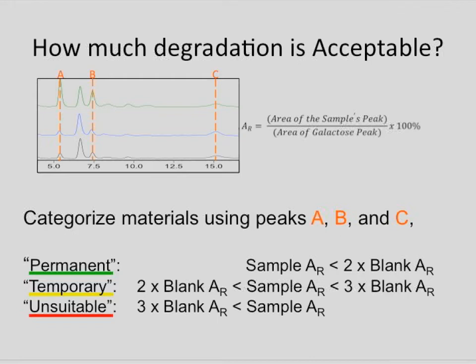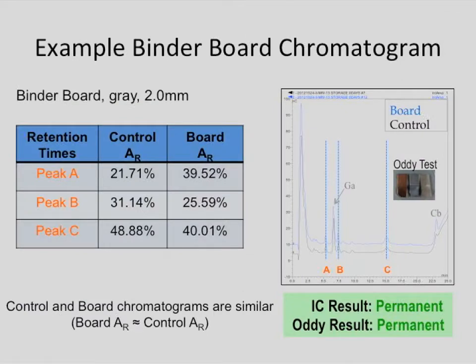Then we ask, how do you say it's temporary, permanent, or unsuitable for use with collections? This is arbitrary, just like the Oddy test, except now we have numbers to look at. We arbitrarily chose less than 2 times the area of the test material peak relative to the control. If it's between 2 and 3 times the control, we call that temporary. If it's more than 3 times the area, we call it unsuitable. That was totally arbitrarily chosen, and later you'll see whether that kind of works.